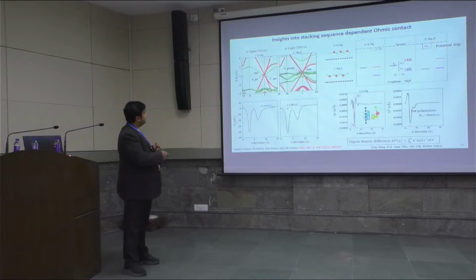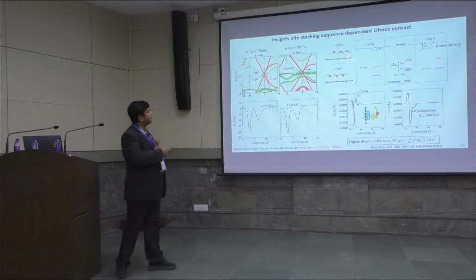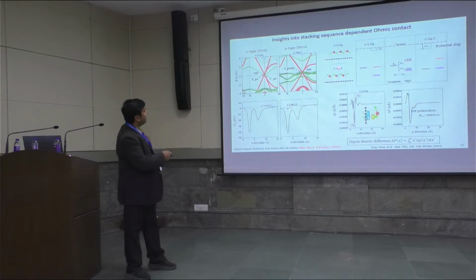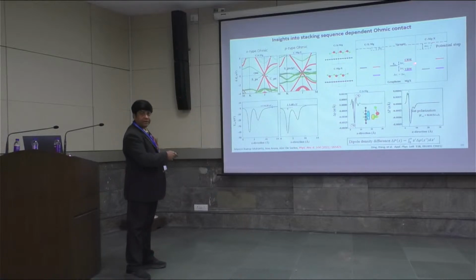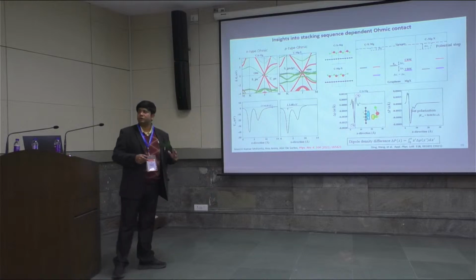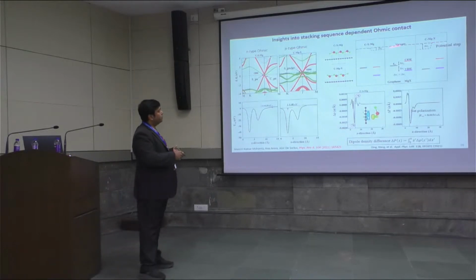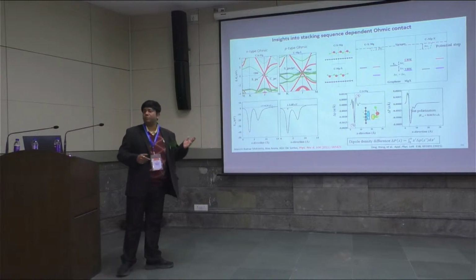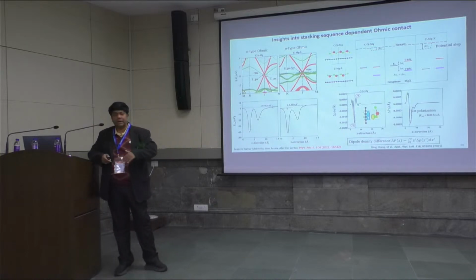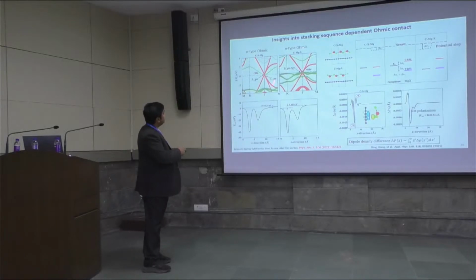Now the nature of the ohmic contact, whether it is an N-type or a P-type ohmic contact, is found to be sensitive to the stacking sequence, whether the chalcogen atoms face graphene or the magnesium atoms face graphene. This is the band alignment on the absolute vacuum scale, and when the van der Waals heterobilayer is formed, the potential step is different. It varies from one to the other because the interfacial polarization varies from one stacking sequence to the other. So in the end, we get an N-type ohmic contact in this stacking sequence and a P-type in this case.